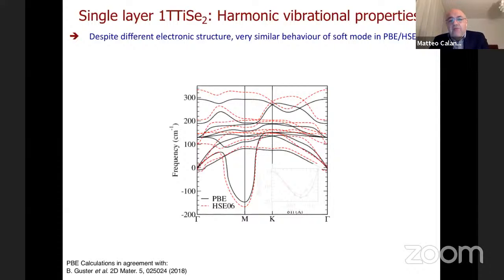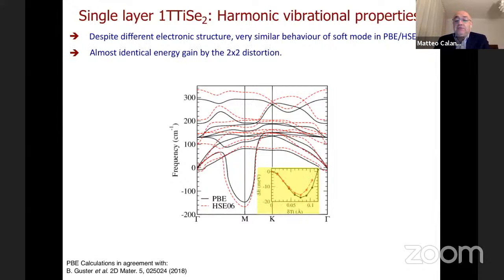So at the harmonic level you have an instability, and you can see that despite the different electronic structure, the phonon dispersion is practically identical in the two functionals. It means that the system behaves as if the electronic structure is not so important. This is also evident if you displace the titanium atoms along the pattern of the charge density wave distortion. The energy gained by the distortion is almost identical in the two functionals. These calculations are essentially in agreement with previous calculations of Bianco and co-workers.